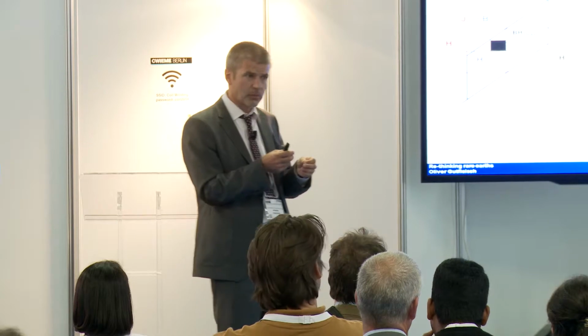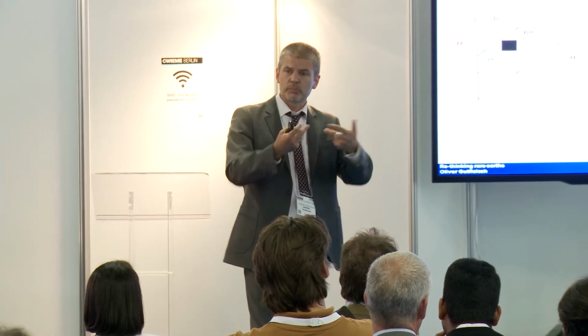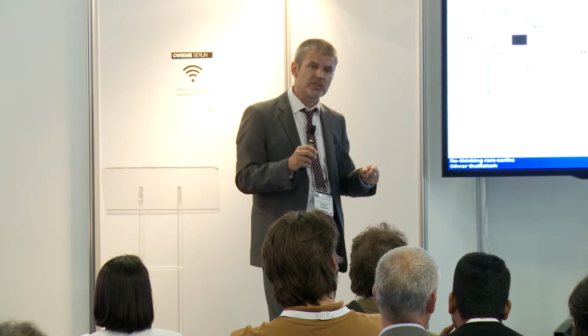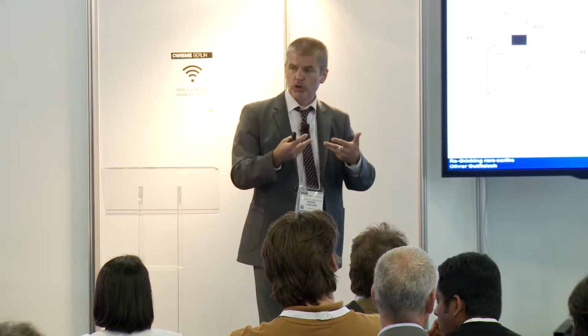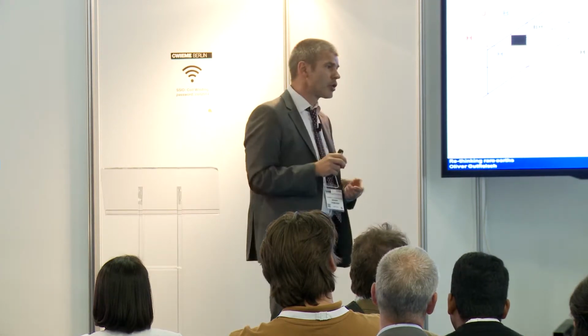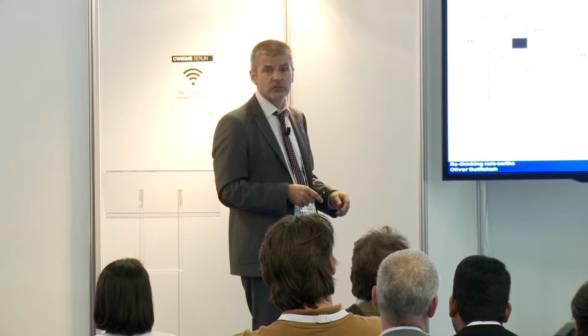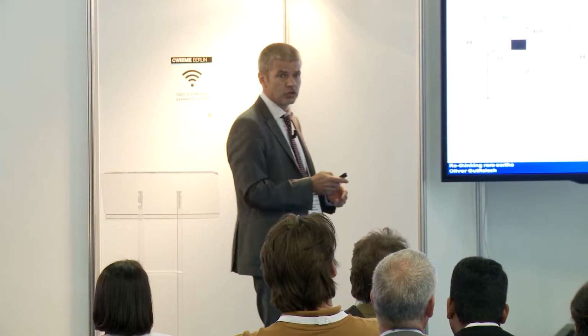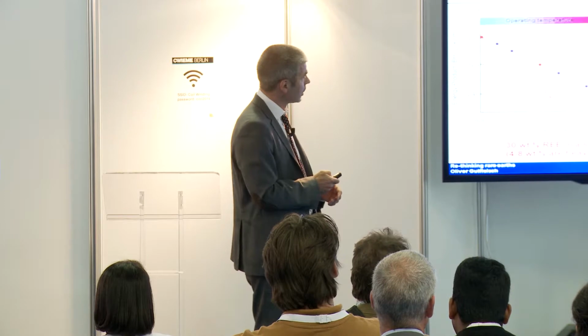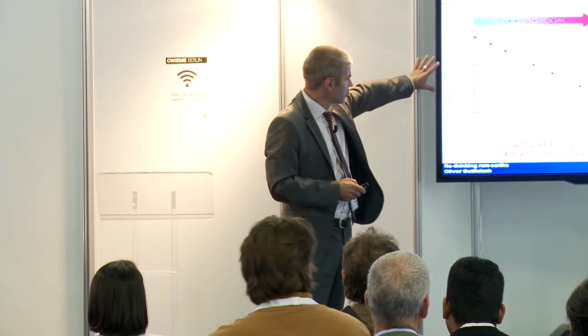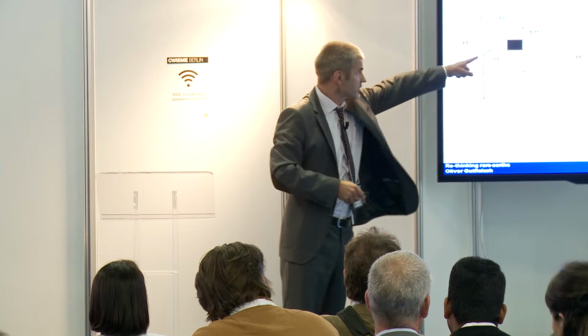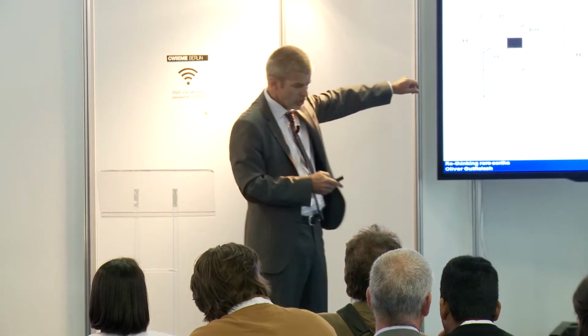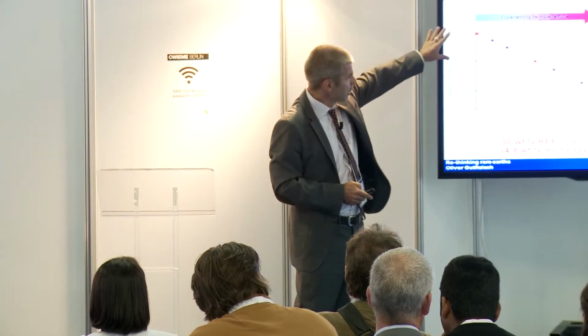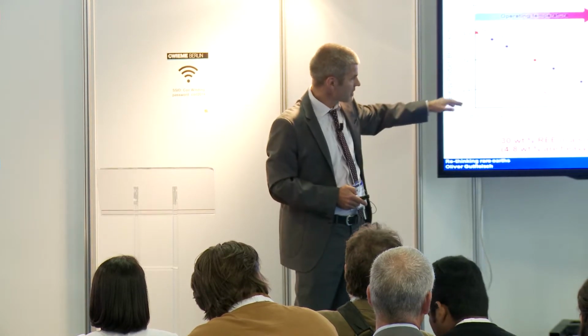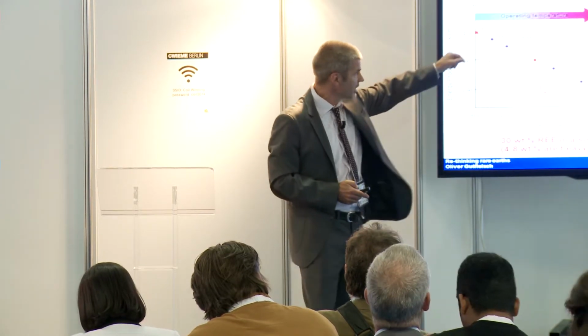Since the discovery of neodymium iron boron, we have not found a better material, but this also had certain physical reasons, because this structure is very close to a perfect magnet, if we could draw one up, in terms of its unit cell structure. So what is happening here? This energy density is plotted, this square here in the hysteresis loop, B over H. And you can see how the energy density or the remanent polarization develops versus coercivity and operating temperatures.